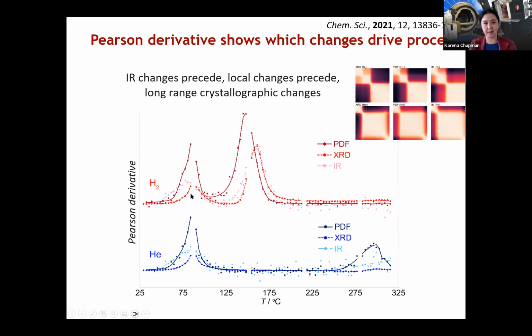So really what this is telling us is the changes in chemistry, the water speciation on the surface of the zeolite, happens before you start to see changes in the silver moving around, which is what you're sensitive to locally in the PDF. And that happens before you have a coupled, correlated, long-range change, which is what you're sensitive to in the XRD. So really the control parameter here is what is happening in the IR, it's the change in the water and the removal of water from the system.